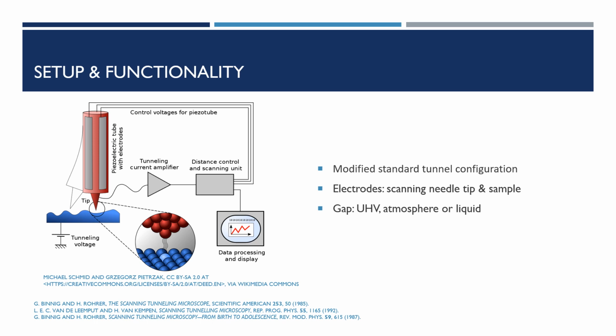Now we come to the setup and the functionality of the STM. To build the first STM, the already known standard tunnel configuration containing the two electrodes separated by an insulating layer was slightly modified. One electrode, here the blue one on the bottom, was replaced by the sample, but this also means that the surface to be investigated has to be conductive. The other electrode is replaced by a very thin, at its best single atomic, scanning needle tip.